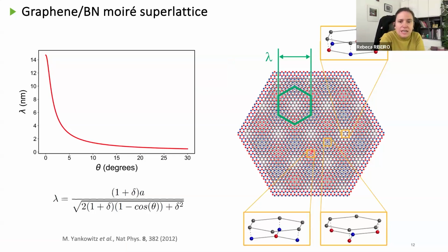So, for example, here you can see, if you focalize in this part where you can see only red dots, that the hexagons of graphene in this area will not have the same environment as another one nearby, okay? But at a certain distance, called lambda, that is the size of this moiré superlattice, you will recover again the same environment, okay? So this is the origin of the moiré structure. This different environment in each carbon atom will give you a different charge distribution, so different properties locally. So this is very beautiful, and it's an easy way to understand the moiré superlattice.